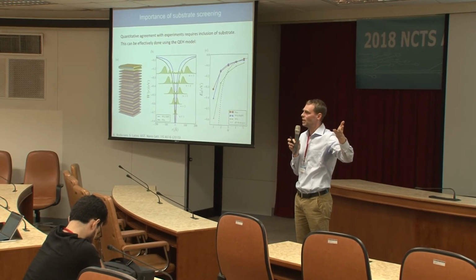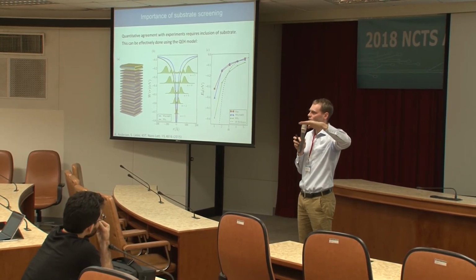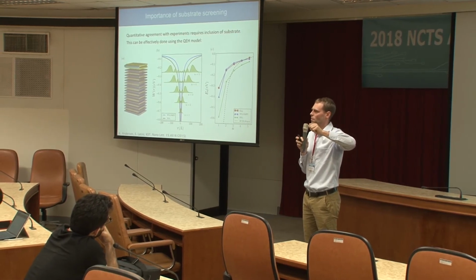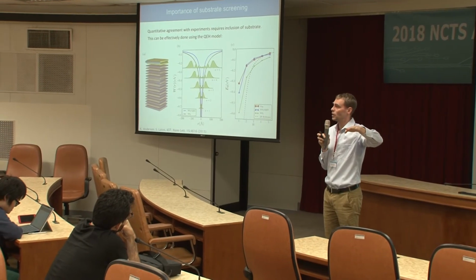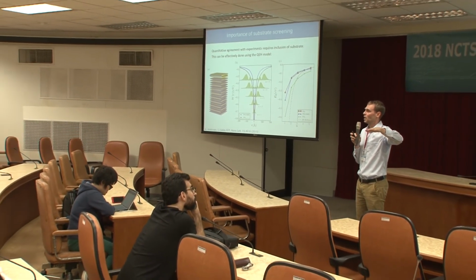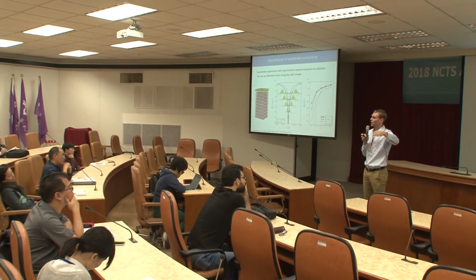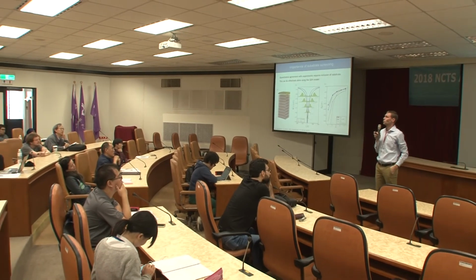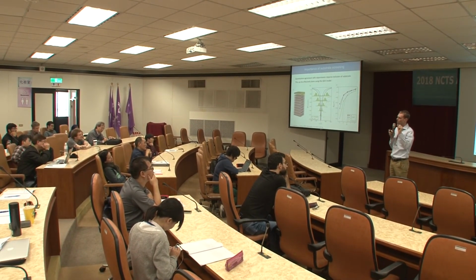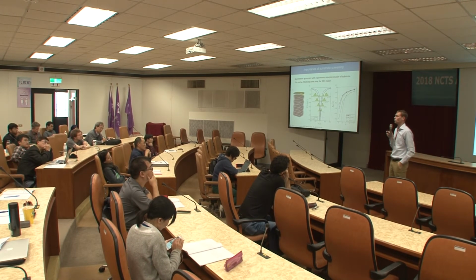So this is essentially a 3D material where the dielectric constant does approach a finite value for Q going to 0. If you use now a truncated Coulomb interaction, then you're describing a physically isolated layer, but the cost you have to pay is that now you have a dielectric function that goes linearly for small q, and therefore the GW band gap will converge slowly with respect to the K points. And that's where this analytical model for describing the dielectric function around q equal to 0 is important.